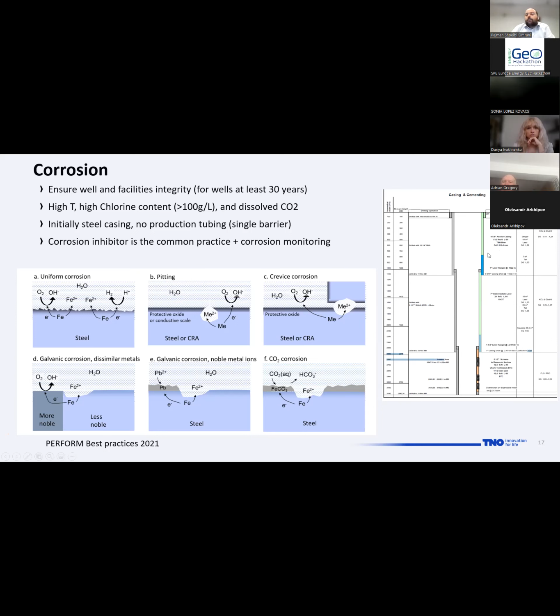What's very important, if you look into most of the early wells in the Netherlands, they have been designed with a single barrier. So this is an example of a completion. There is no production tubing or liner. There's just a single barrier. So you actually start to produce your salty brine at high temperature in the production well. But also initially most of these wells were designed with carbon steel or very low alloy steels. So you already know why corrosion was an issue in this case.